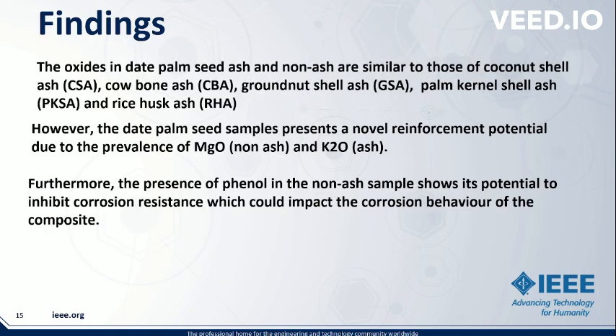Key findings from this study include that the oxides in date palm seed ash and non-ash are similar to those of coconut shell ash, bagasse ash, groundnut shell ash, palm kernel shell ash, and rice husk ash. The date palm seed samples present a novel reinforcement potential due to the prevalence of magnesium oxide in the non-ash and potassium oxide in the ash samples. The presence of phenol in the non-ash sample shows its potential to inhibit corrosion, which could impact the corrosion behavior of the composites.